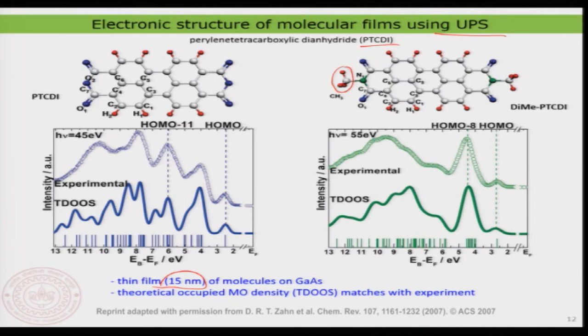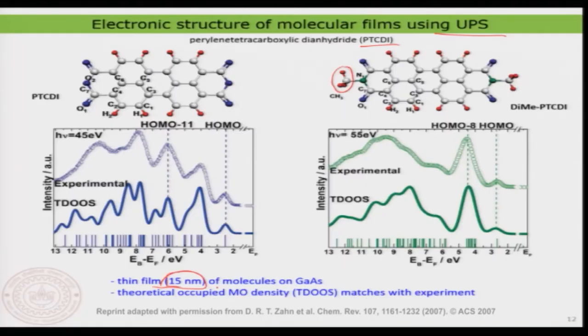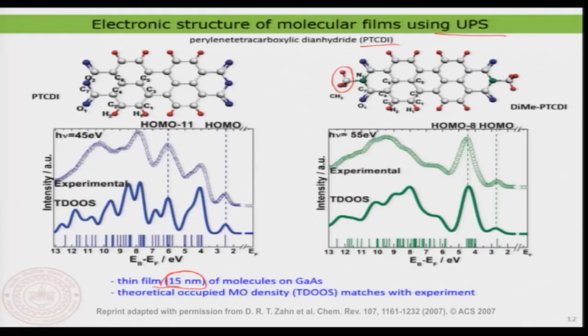When you look at scanning tunneling spectroscopy or scanning tunneling microscopy, you are always trying to look at things in greater detail. You are trying to look at what happens to the molecule when it adsorbs, what the electronic structure of a single molecule is, and so on. Those are the kind of questions you put forward with scanning tunneling microscopy, because it has that possibility. But when it comes to ultraviolet photoelectron spectroscopy, you go a little bit bigger. In this case, I'm looking at a 15 nanometer thick film of molecule on a gallium arsenide surface. And now I can measure the density of state of the molecule.